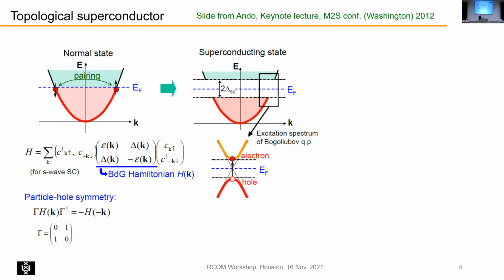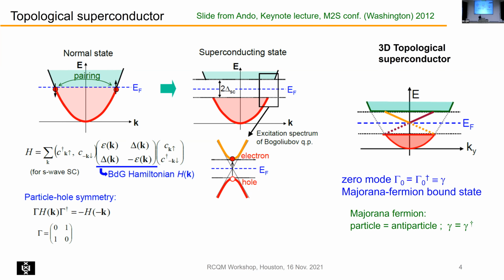Now in a topological superconductor, a 3D topological superconductor, you also have a bulk gap, a superconducting gap, and you also have excitations in the gap, or actually these excitations are only on the surface, that's important. And if you see here at zero energy, that is the Majorana fermion bound state. I took this from a slide from Ando already quite a while ago. So actually we're after a system where you could have bulk superconductivity, topological states on the surface, and these would then harbor these Majorana states.